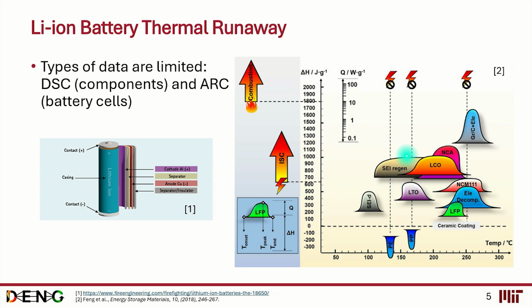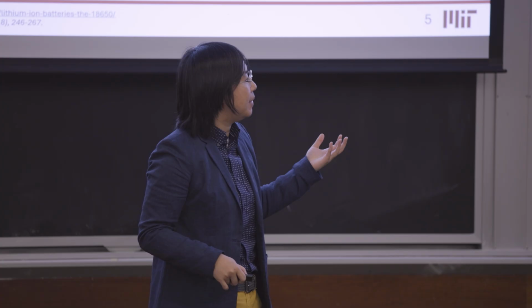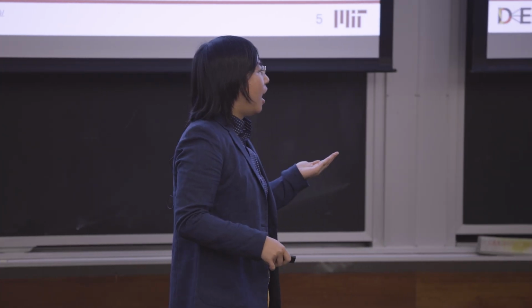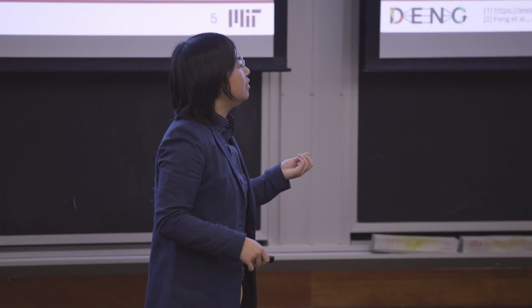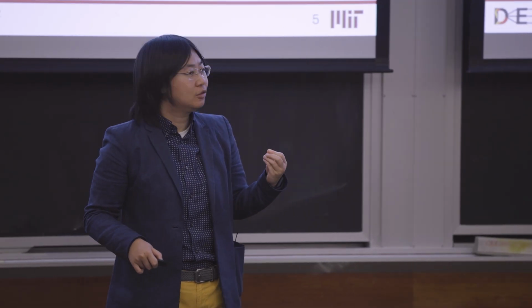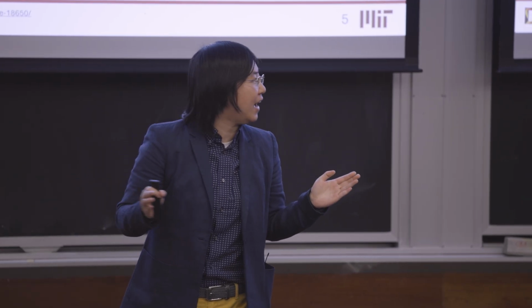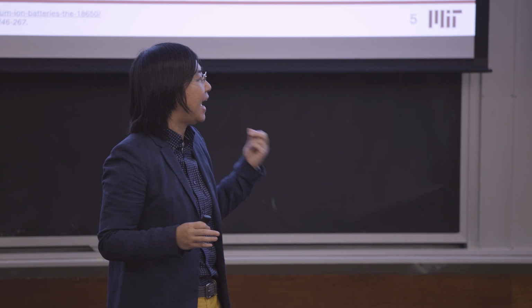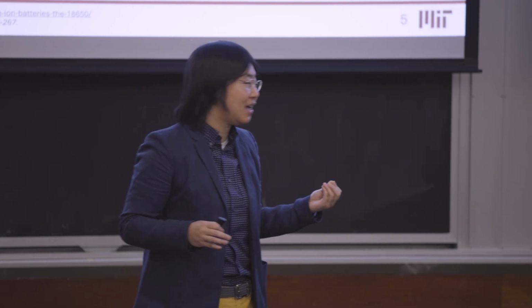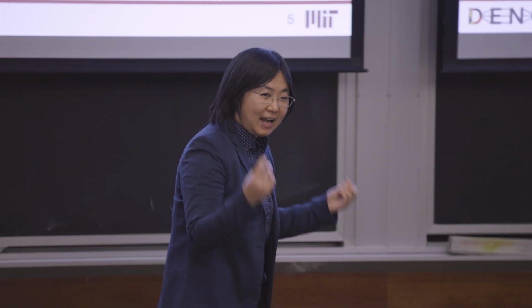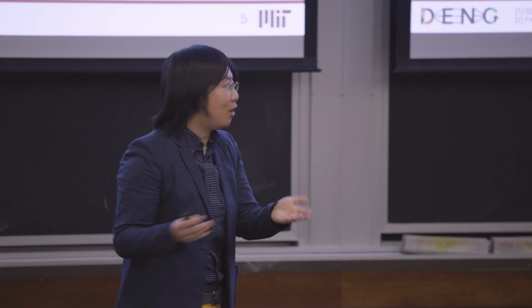However, for the cathode materials, essentially they are transition metal oxides or transition metal mixtures. They can thermally decompose such that oxygen can come out of the matrices and then become oxidizers in the system. And we all know the electrolytes are prone to combustion, so they are combustible, flammable. So imagine you have an environment of elevated temperature, and then you have the gas oxygen generated from the cathode, and you have a flammable electrolyte. They are together, you are in trouble, right?